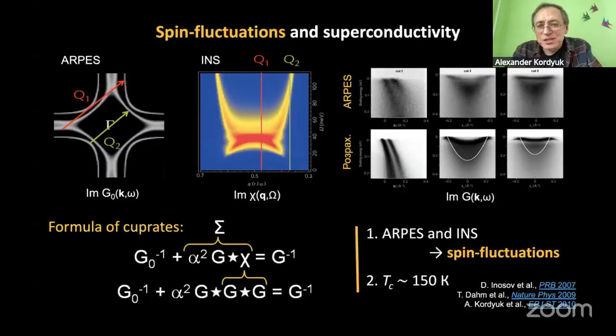And to do it, you need to compare angle and momentum resolved results. You need to have a momentum resolved electronic structure and compare it with the momentum resolved structure of the excitation spectrum, the spectrum of phonons or other spectrum. And it appears, from my point of view, and many people agree with this, but there are still some people who believe in phonons in high temperature superconductors, but most probably this glue between electrons is made by exchange of spin fluctuations. So instead of phonons, you have spin fluctuations, and from such a comparison of the electronic band structure with the structure of spin fluctuations, you see that they are consistent in a sense.